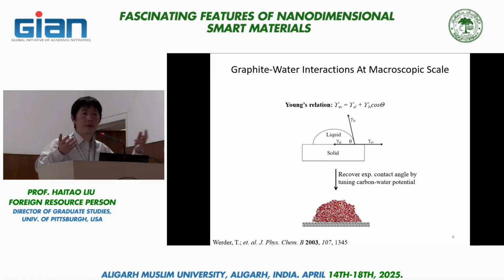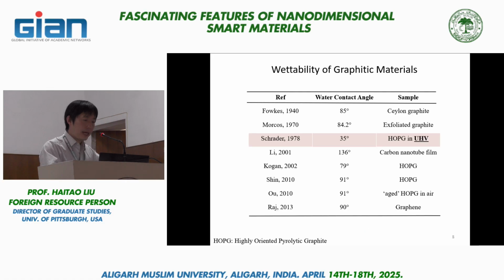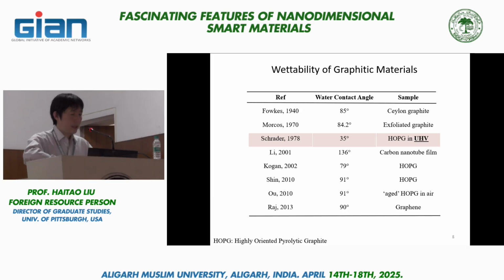vacuum. And when that happens, the contact angle will go down because you're getting rid of water in that droplet. So people don't really take seriously this 35-degree value that Schrader reported in '78. You also notice there are sometimes very large values, 136, but this is due to a topography reason, because the carbon nanotube produces a porous structure, and that is a known contributor to increased water contact angle on a hydrophobic surface. If you make the surface rough, it usually increases the apparent hydrophobicity.